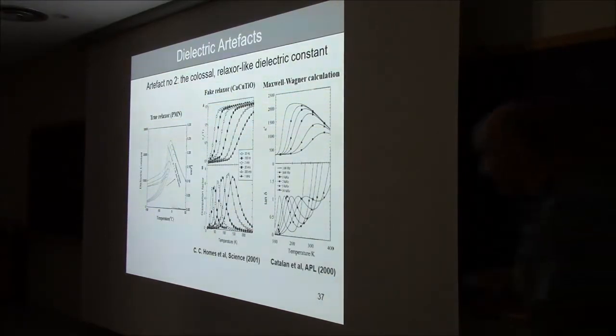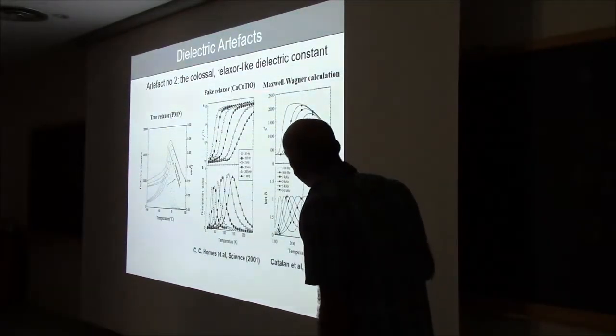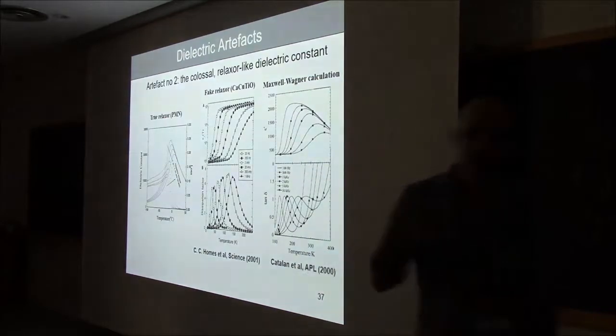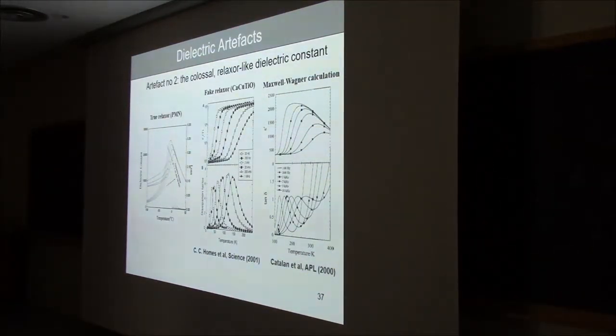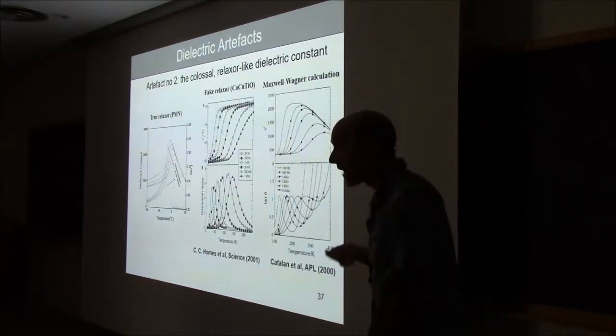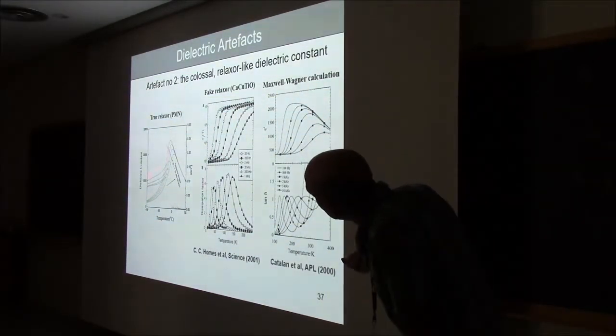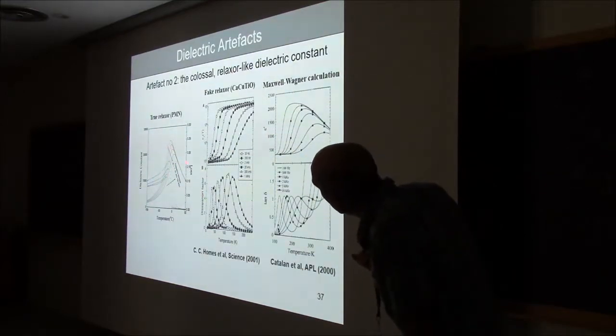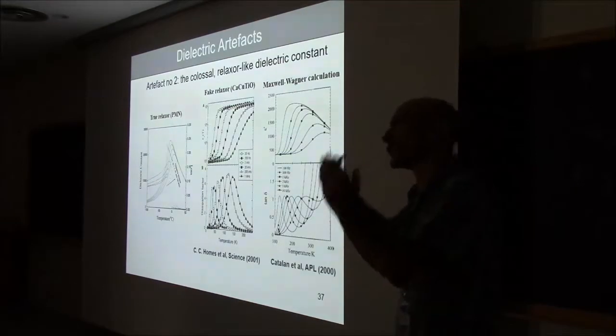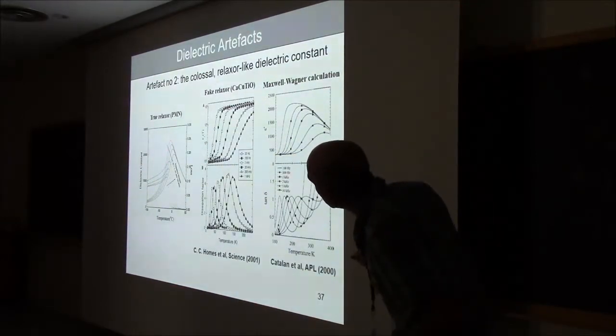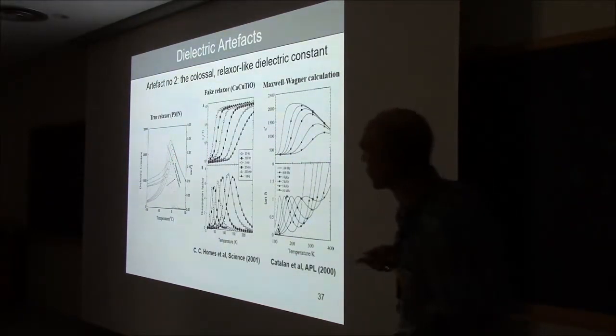There's another important artifact that I want to stress, which is a colossal relaxor-like dielectric constant. And this is also ubiquitous in the literature. Every time a new field becomes fashionable, like multiferroics or photovoltaics, someone claims to have seen a relaxor-like giant dielectric constant in their material, which is nothing of the sort. To remind you what a relaxor dielectric constant looks like, this is it. Okay, so you have something that has a temperature dependence, but it's not a very sharp temperature dependence, and the maximum of the dielectric constant shifts as a function of frequency. That's one of the features of relaxors.